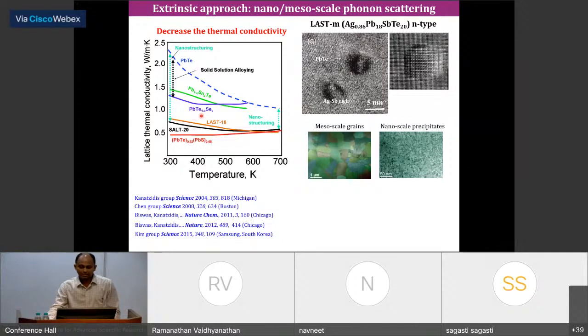But starting from 2004, a bunch of materials were discovered which are actually nanostructures. And nanostructures can be embedded in a solid bulk matrix of thermoelectric material such as lead telluride and bismuth telluride, where these nanostructures are exactly the same size as the phonon wavelength. So it can scatter phonons heavily and decrease the thermal conductivity and can create high performance thermoelectric material.